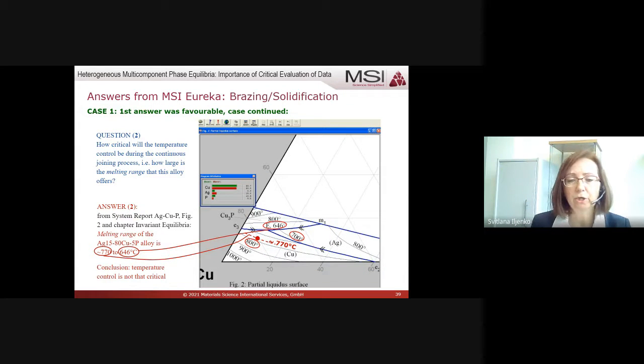The next question may then come in this case: how critical will be the temperature control during this joining process? And how large, actually the question is how large is the melting range that this alloy has. This one can get by looking at solidus and liquidus temperatures, and the melting range, so the end of melting is 770, and it starts melting at this eutectic temperature, 646 degrees. So that means that the melting range is between these two temperatures, and the temperature control for this device will be not critical. That's quite a convenient, good candidate.